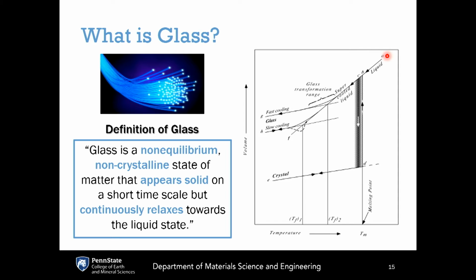Now, what happens as you cool the liquid? If you cool the liquid to just below its liquidus temperature, what will happen in equilibrium? It will undergo a first-order thermodynamic phase change with a discontinuous change in all of our favorite thermodynamic properties, the volume, the enthalpy, the entropy, and it crystallizes. And so the new equilibrium at lower temperatures is the crystal. And if you continue to cool, the crystal will contract according to its thermal expansion coefficient.